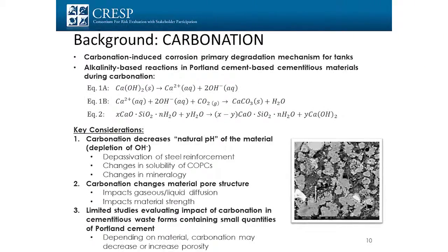Carbonation is recognized as one of the primary degradation or aging mechanisms for empty tanks at, say, Hanford. So it's important from that respect. There are a number of reactions that can happen as you get CO2 from the soil gas or from the atmosphere in contact with the concrete. It can lead to changes in pH, which if you have a significant change in pH, say to pH 9, you can get depassivation of embedded rebar. That can lead to expansion, maybe even cracking. So it's something that could change the structural properties as well, the advective property, the flow properties of the material. It'll change the solubility of certain key constituents that you care about. Like I said, the microstructure can change.